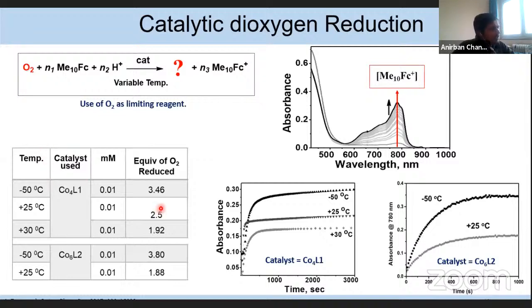In this table, I show how many equivalents of oxygen were reduced using 0.01 millimolar complex as catalyst. At minus 50 degrees centigrade for the tetranuclear complex, I found around 3.5 equivalents of oxygen reduced, which corresponds to water, whereas at higher temperature the amount of oxygen reduced is 1.92 equivalents. So 2-electron oxygen reduction takes place, which corresponds to hydrogen peroxide. Similarly, for the cobalt-6 complex at low temperature, the amount of oxygen reduced is around 3.8 equivalents, which again indicates 4-electron oxygen reduction, whereas at high temperature the amount of oxygen reduced is 1.8 equivalents, which indicates 2-electron oxygen reduction to hydrogen peroxide. However,